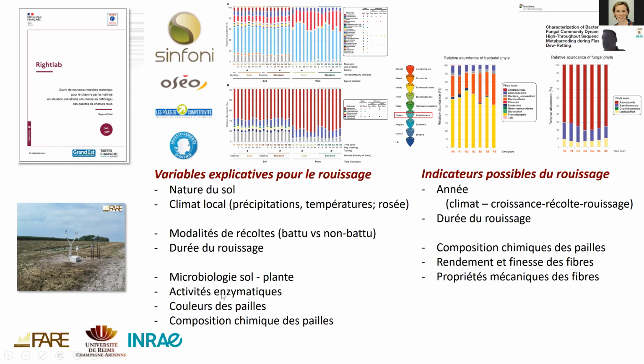Also enzymatic activities: we have oxidative and hydrolysis, and we have to have the combination of the two for a good rating. Other parameters that can be used are the color. You see that it's quite gray here, and at the beginning it's not this kind of color, and also the chemical composition. And then, after trying to make correlations between several parameters, some main indicators could be used.